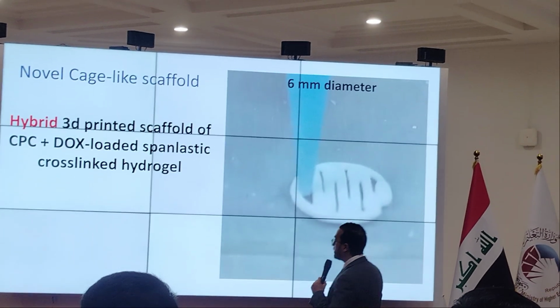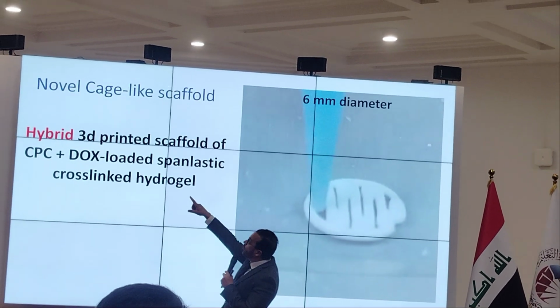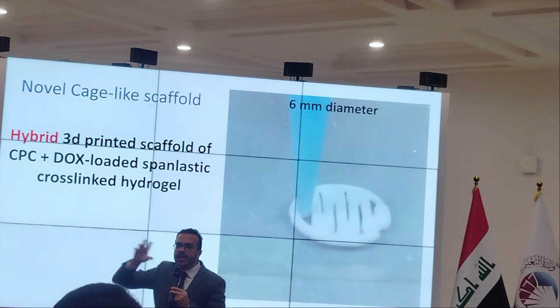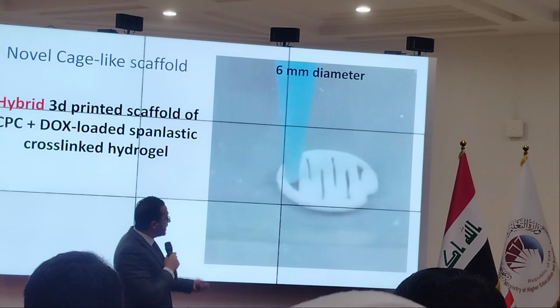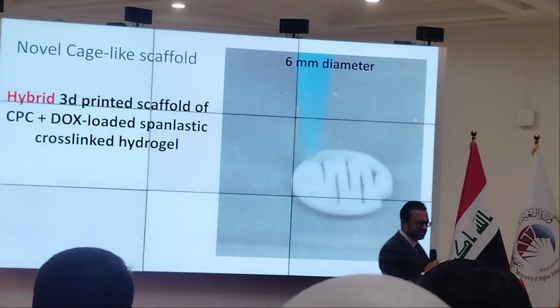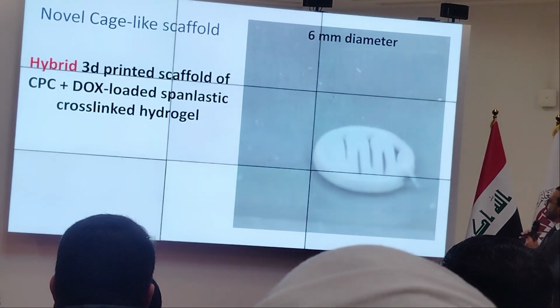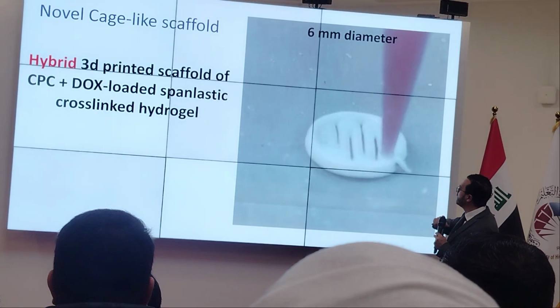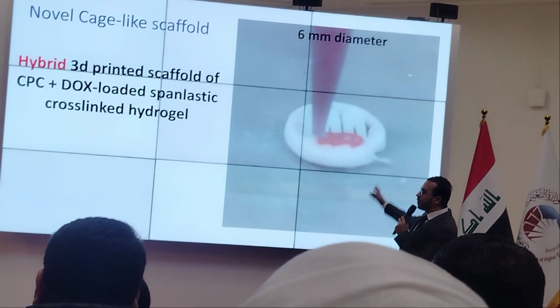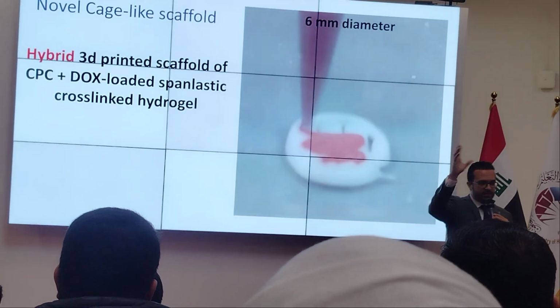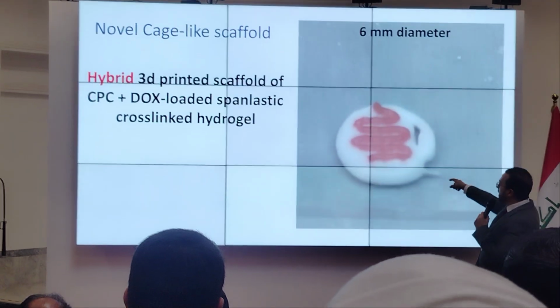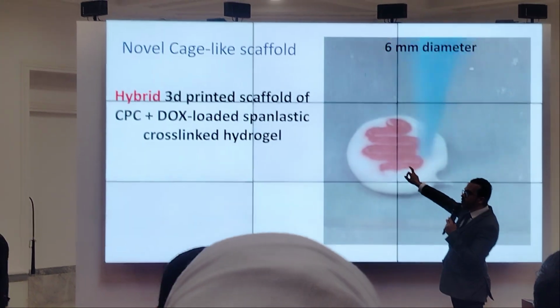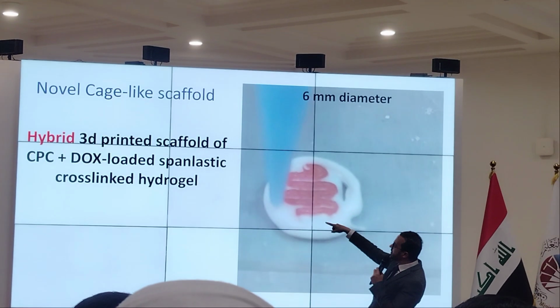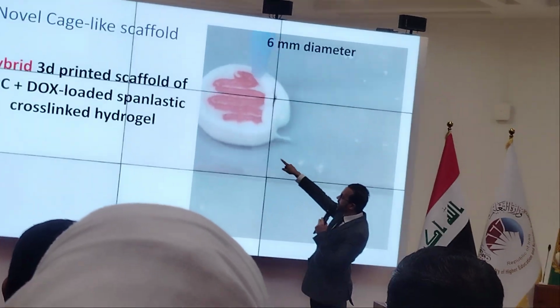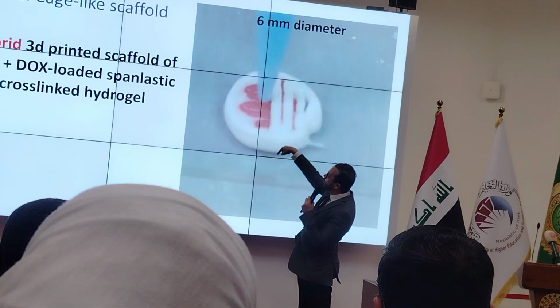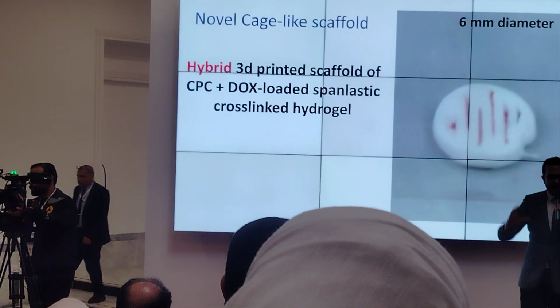So the last design here, we came with a final design of what is called a cage-like scaffold. As you can see here, we have a cage-like scaffold made from calcium phosphate cement, and the core here is filled with gel loaded with nanocarrier loaded with doxorubicin. And you can see the bottom and walls are from calcium phosphate cement, the white material, in a cage-like structure.